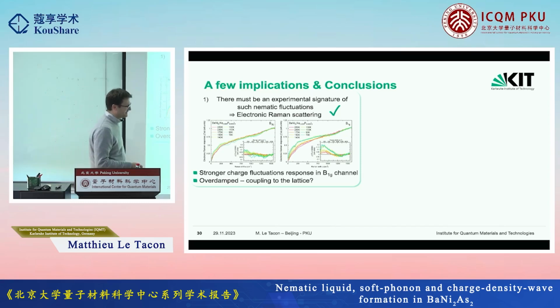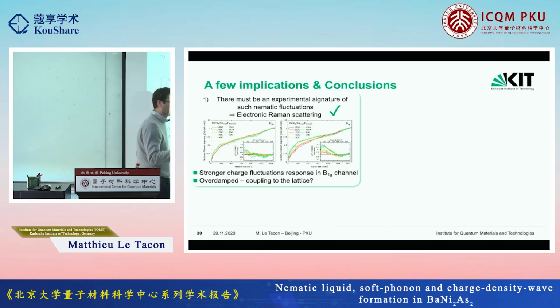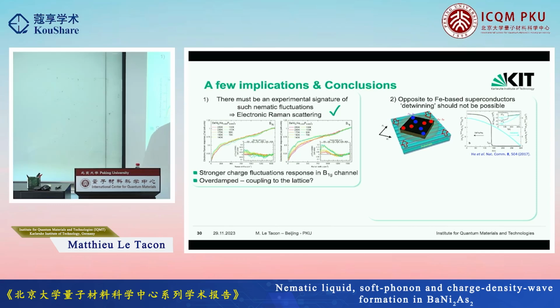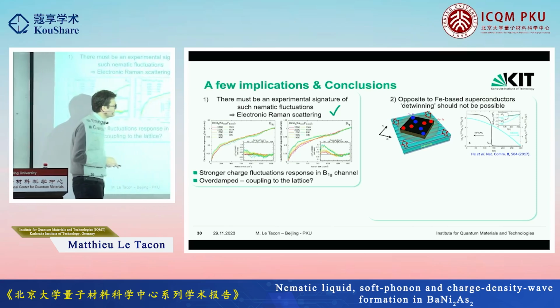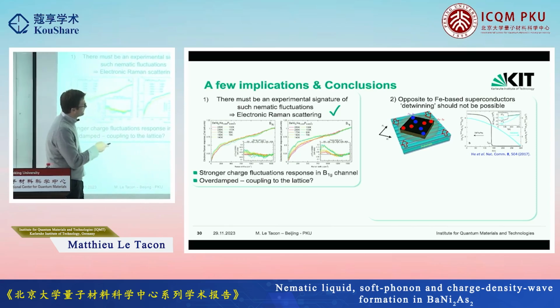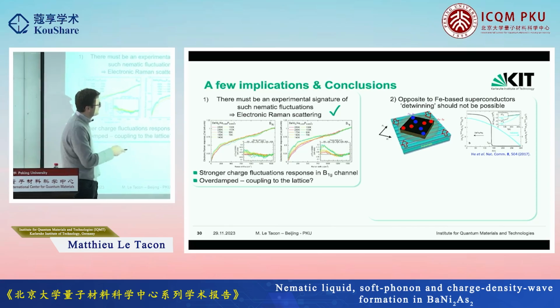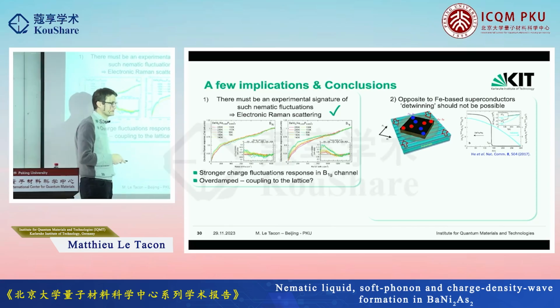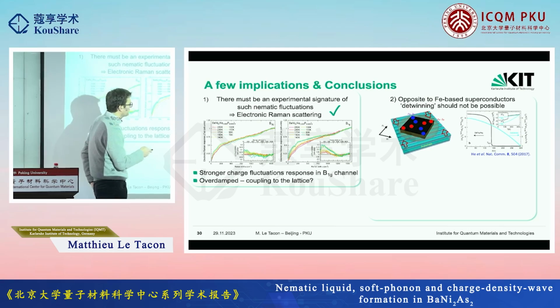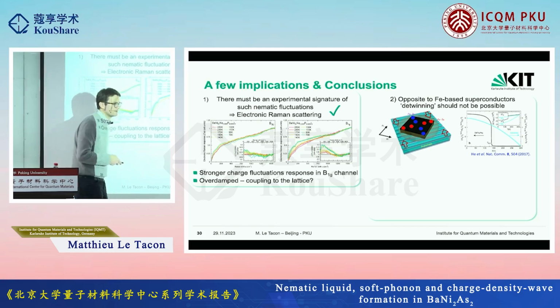Is that, well, if you have a tetragonal system and you do have those fluctuations, you should not be able to detwin the system because there is nothing to detwin. In the iron-based compound, you can glue your sample onto a kind of substrate which has an anisotropic thermal expansion, and that is sufficient to align all the domains of the sample.